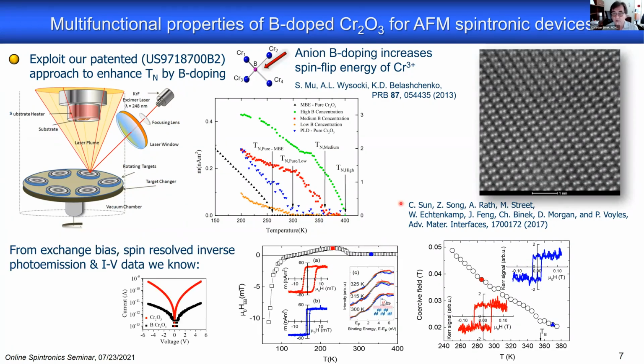And now, of course, we were naive and we said, okay, we got it. We have the increased Néel temperature. Now let's make perpendicular exchange bias systems with them. And that gave some interesting and some frustrating surprises. So first of all, when we tried the perpendicular exchange bias, to make the story short, we found absence of exchange bias. There was no significant pinning, but we did see loop broadening at what people call the blocking temperature, which was above the 307 of pure chromia.